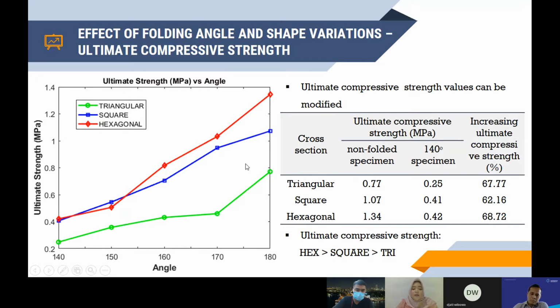As the pre-folded angle is introduced, the ultimate compressive strength can be modified into a lower value. This means that by introducing the pre-folded pattern into a thin-walled column structure, the compressive strength can be designed as needed for the application. If we compare triangular, square, and hexagonal, the triangular specimen shows the lowest ultimate compressive strength compared to the square and hexagonal. As shown in the table, the ultimate compressive strength of the hexagonal specimen is almost twice the value of the triangular specimen. The possible reason for this result will be discussed in the discussion part.